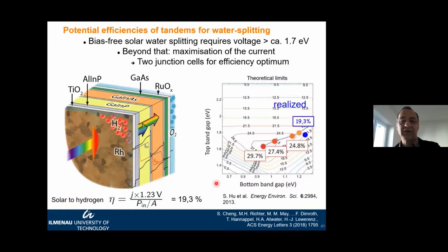Show this. You see a contour plot of the combination of the two subcells in such a tandem structure. You can see the bottom band gap, which is shown here on the x-axis, and the top band gap, which you can see on the y-axis. And if you combine both, for example, in the ranges of 1 eV and 1.7 eV or so, then we are here more or less in the bull's eye of the efficiencies.